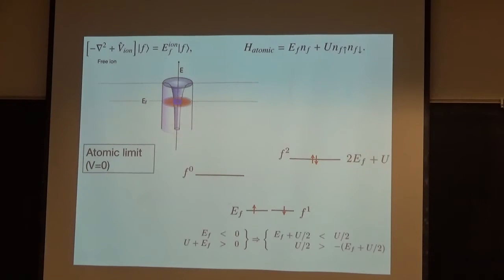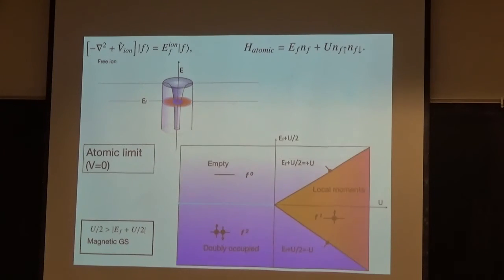And under those two criteria, you can rearrange this, just a little rearrangement here, that E_f plus U over 2 is less than U over 2, and U over 2 is greater than minus E_f plus U over 2. And that then gives the famous phase diagram for the Anderson model, the atomic limit. There are three basic phases here, and the one we're interested in is the local moment phase here. For U positive, if you're in this region here, the ground state is a local moment. And so if U is large enough, then you can forget about the f0 and f2 state, and you integrate those out. That then gives you the Kondo model. How is that done?